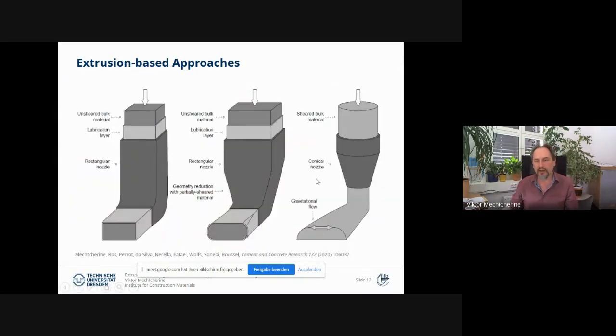So let's go further, and I will try to summarize with this image the different approaches for deposition of the material. On the left side we have what we call the infinite brick. It means very stiff material pressed through the nozzle, with no deformation upon deposition. On the other hand, on the right side of the image, you see the approach where we have very flowable material, which is highly accelerated. After some flow under gravity, we forcefully reach the final shape, and this shape is then kept as it is. Due to progressive stiffening and hydration, we have the possibility to carry further layers.